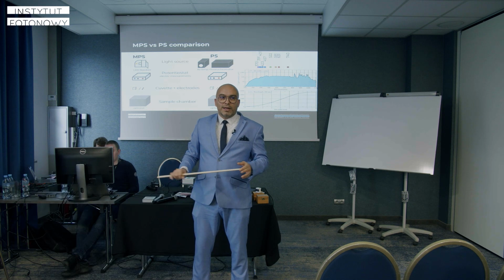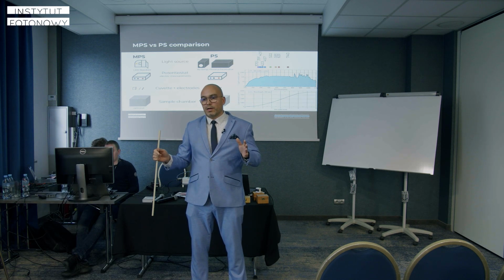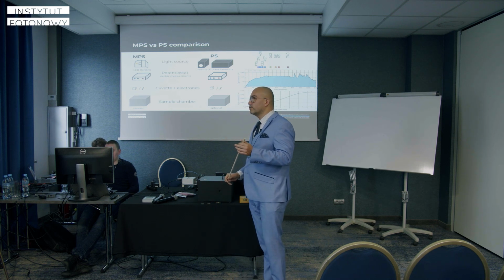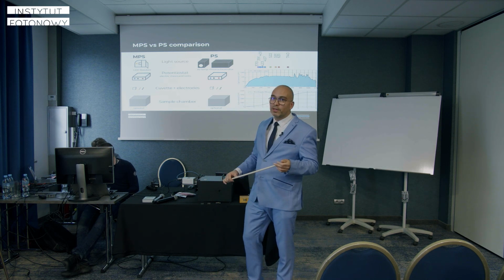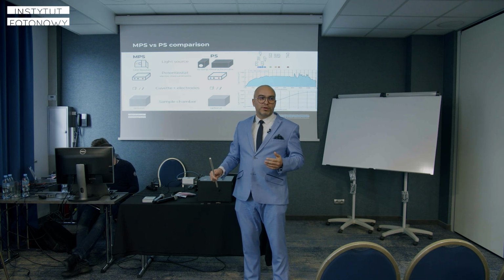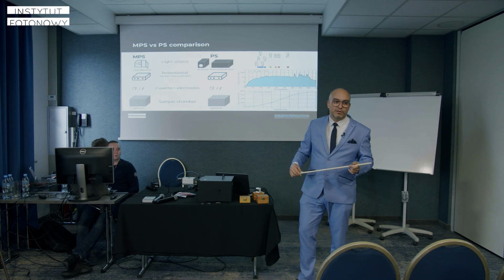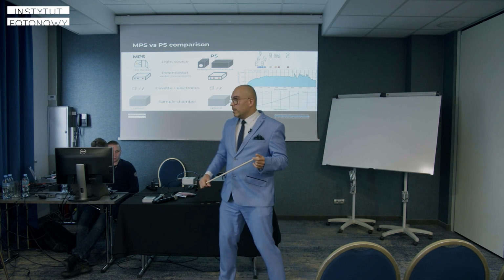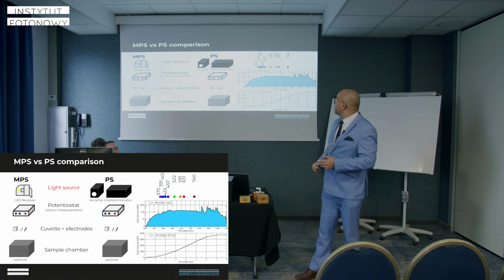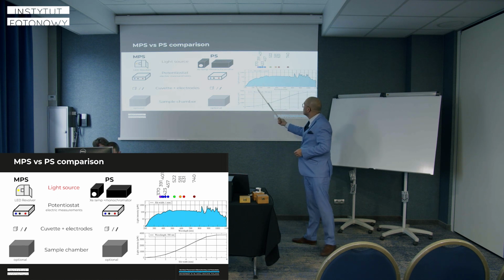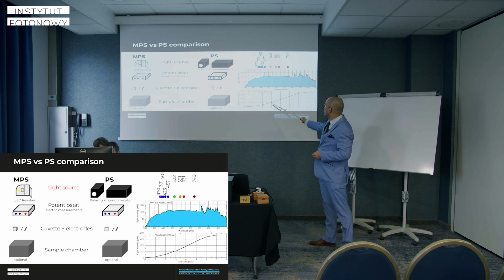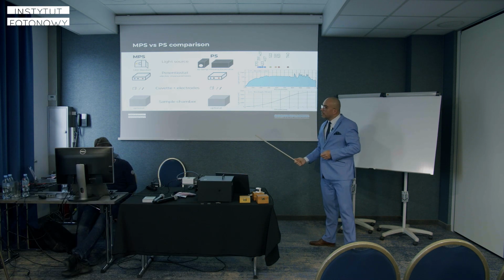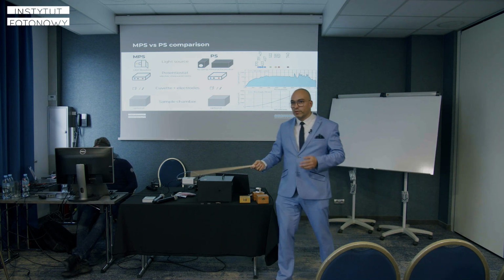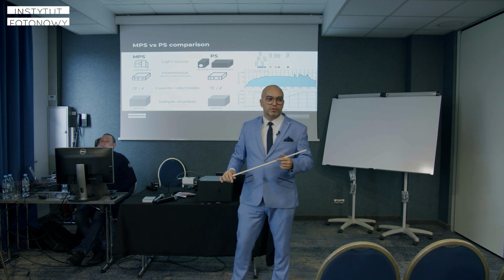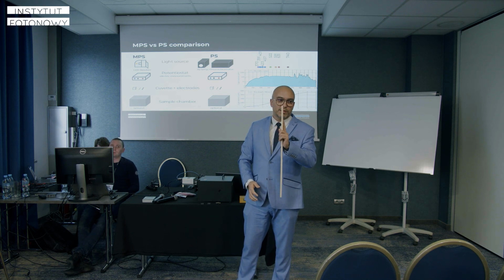the advantage of the xenon lamp is that it has a large power. This is 150 watts electric power, but this power is mostly used to heat up the cooling water in the cooling water circuit. And after the monochromator, we only have some fractions of watts, some milliwatts or so in that range, and it also depends on the slit width. And in the case of the LED revolver, we just deliver about 1-3 watts of power exactly to power this narrow line.